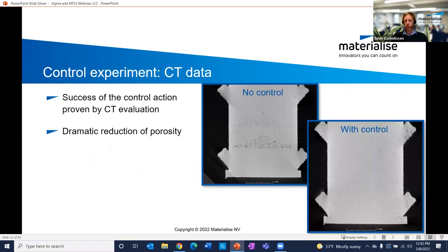We have obviously also taken a CT scan of the sample with control, and this proves luckily that the data is right, and that where you have in the reference experiment these nice pyramidal shapes with induced errors, in the control experiment those errors have disappeared, and everything looks pretty much uniform, which is exactly what we want.